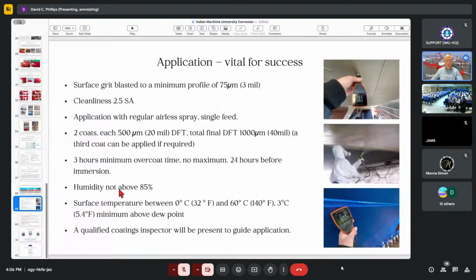The conditions for application: the humidity needs to be 85% or less, and the surface temperature of the ship hull or whatever has to be between 0 and 60 degrees, which is quite a wide window. It needs to be 3 degrees above the dew point or more. Otherwise, you get condensation, which affects the application. But that's it. It's not very stringent requirements. Shipyards are quite used to that.